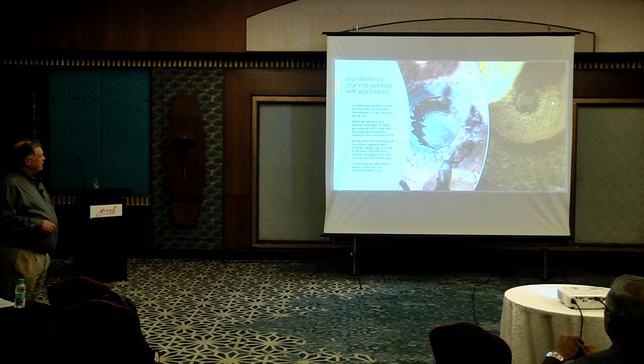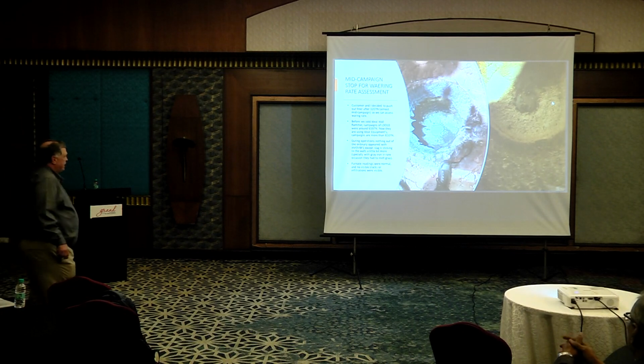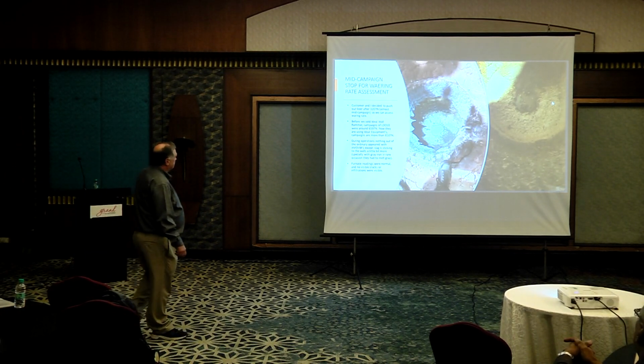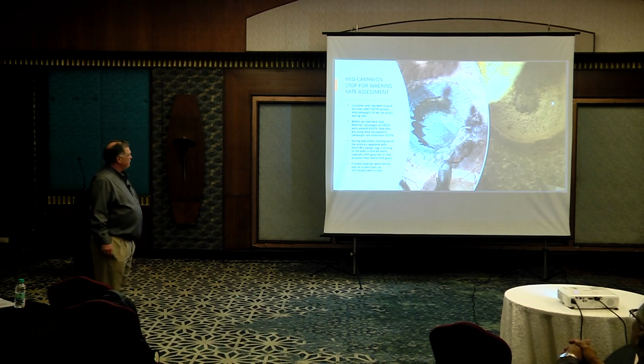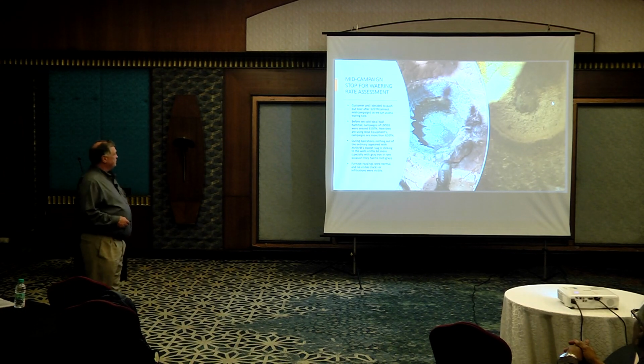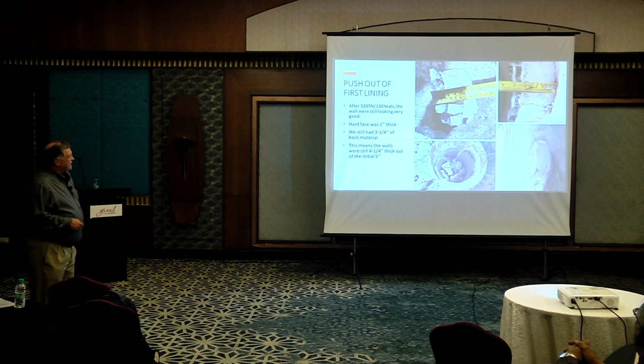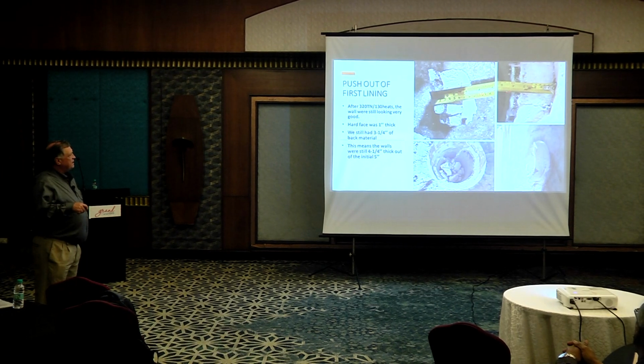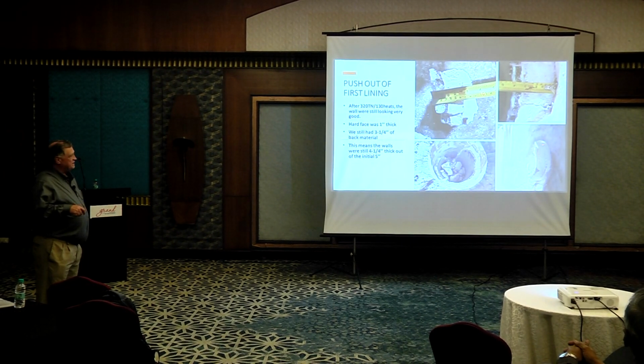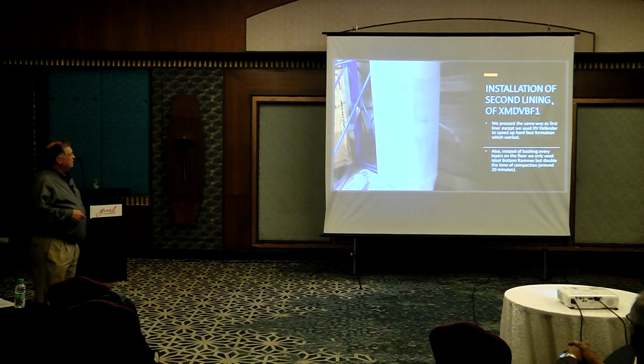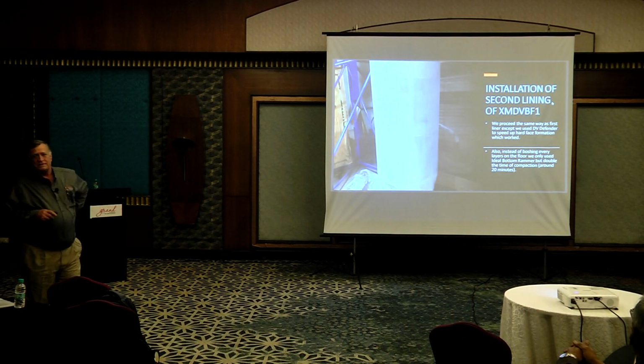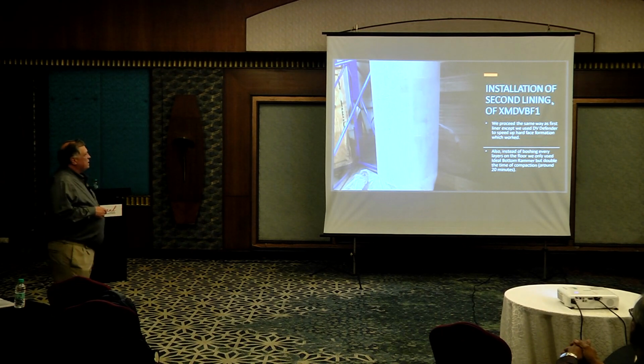So during the operation, nothing out of the ordinary happened with the boron-free silica, except for the walls being a little brittle. Furnace readings were normal, no visible cracks, and infiltration was visible. So then they took it out and they basically analyzed every layer as they were taking it out. As you can see, there's still about 100 mm of lining left in this lining. You can see there was quite a bit of loose backup still present in that lining. So that lining could have gone a lot further. But they took it out again just so they could do an analysis, since it was the first time that they used it.